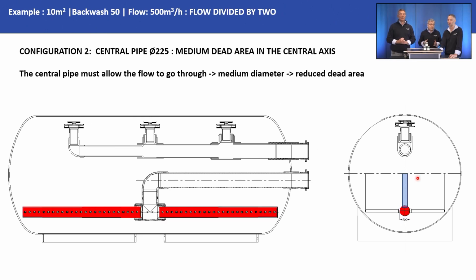If we just change the design a bit and we have a pipe coming to the center, so also we come in with 300, but then we split it in 2 times 225. Then we will have the area reduced. So that's already a much better design. Is that the design you're using? No, it's not. This is not enough. Still longer laterals, as you can see in the picture below. The laterals are very long.